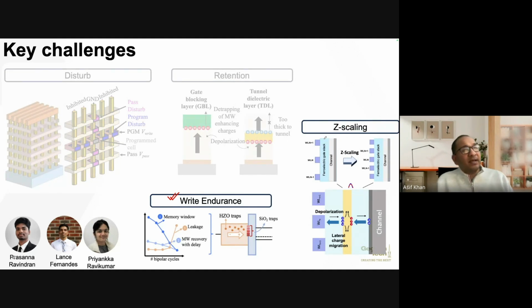The other aspect is how scalable ferroelectrics are in the vertical stacks. This is what we are currently working on: understanding how a ferroelectric field effect transistor behaves in a vertical orientation like this, and how much we can scale the mold height. The key challenge is to understand how the dynamics of polarization and the traps occur as we scale down these device dimensions.